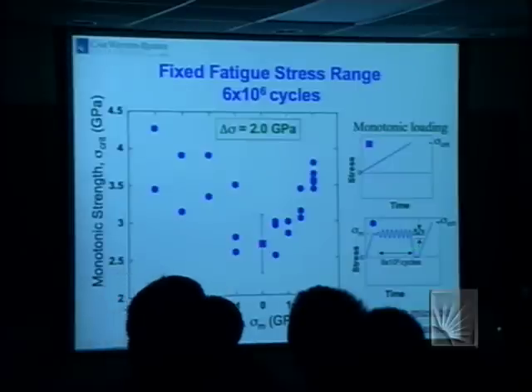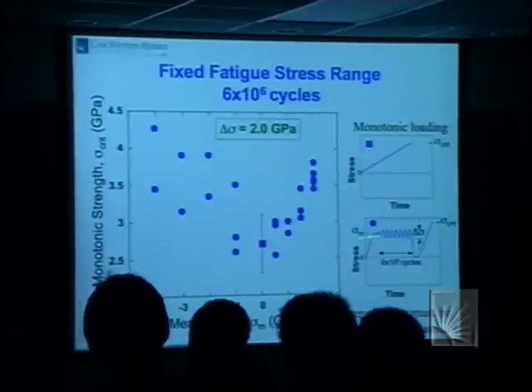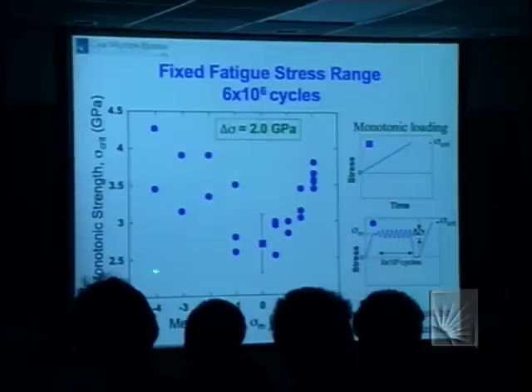We did another kind of experiment, which was also interesting. Again, there's a monotonic strength. This was a slightly weaker batch, with a rougher surface. What we did is we cycled for 6 million cycles at some value of the mean stress, then unloaded and loaded to failure. And at small values of the mean stress, we saw no effect.